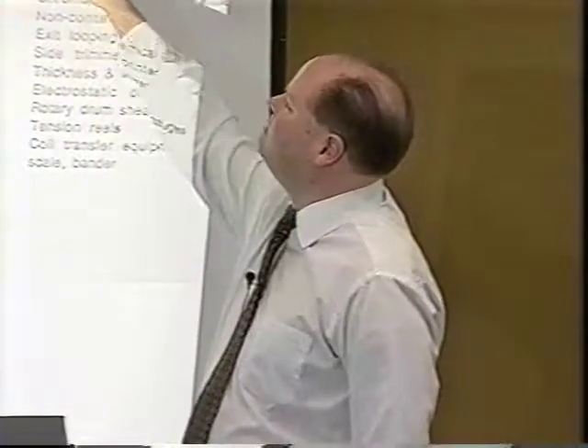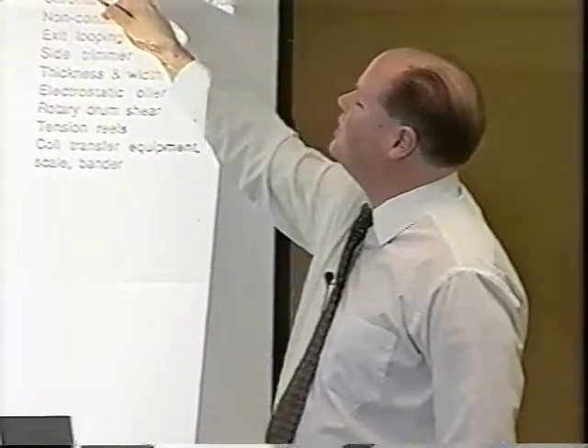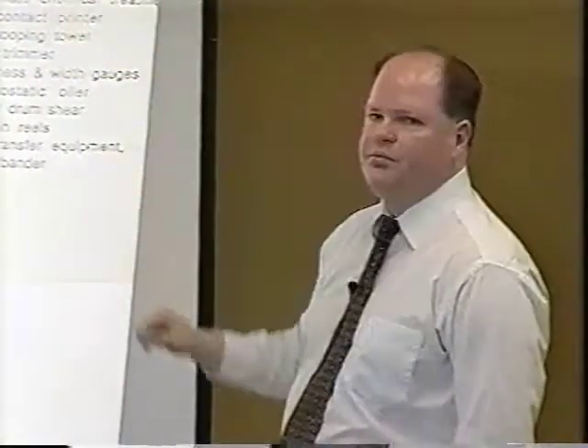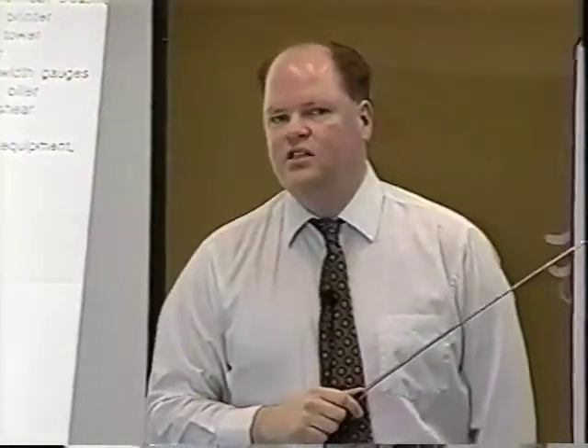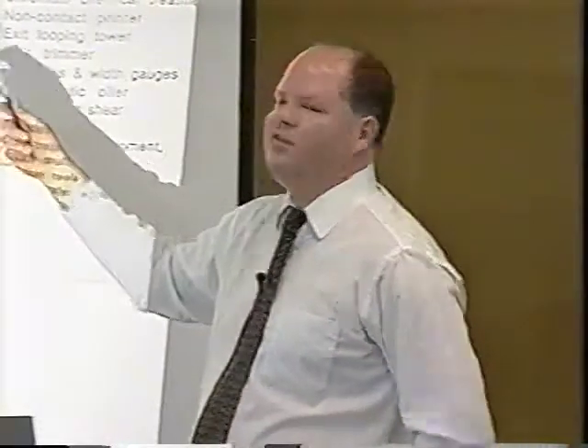but okay, so now we've made either galvanized or galvanneal. We went through the quench tank to kind of cool it down. Then we get to our temper mill and tension leveler. It's a nice feature we have online. We can temper roll it and tension level it right online instead of having to take it and send it to our temper mill. You saw those galvanized samples, and I mentioned how it had a mirror-like surface when it first came out of the bath here, and we actually have to rough it up on our temper mill in order to get a proper matte finish.